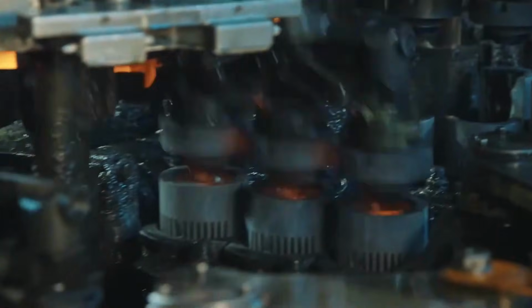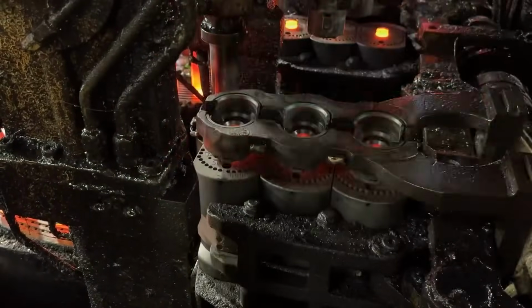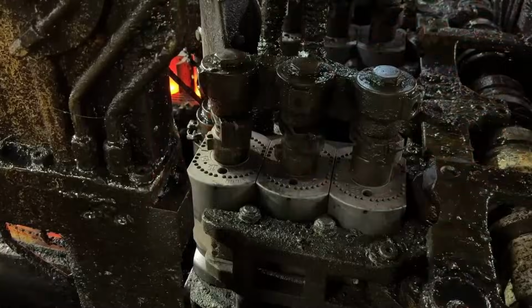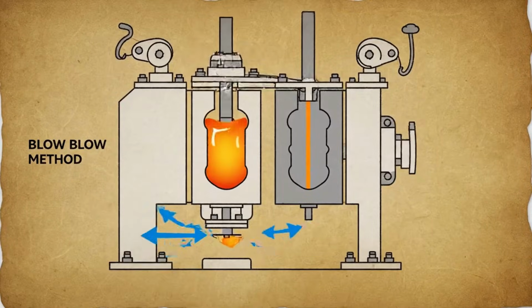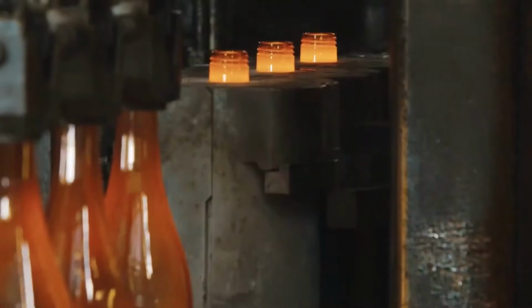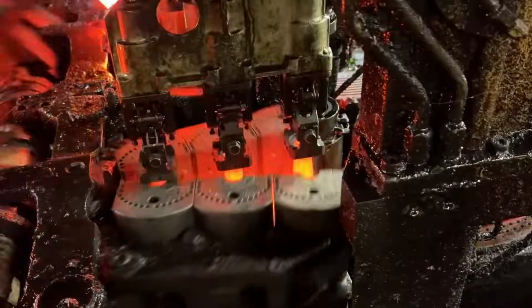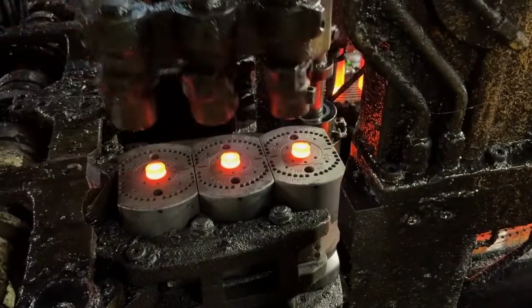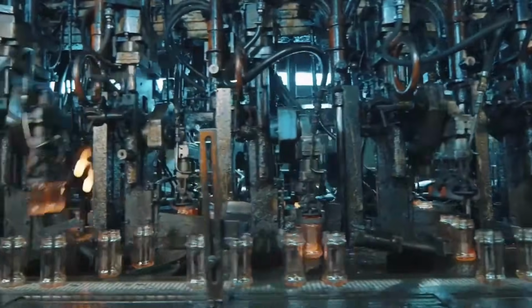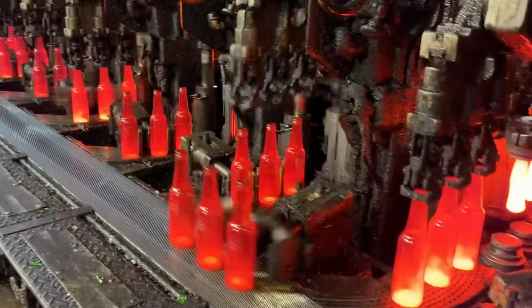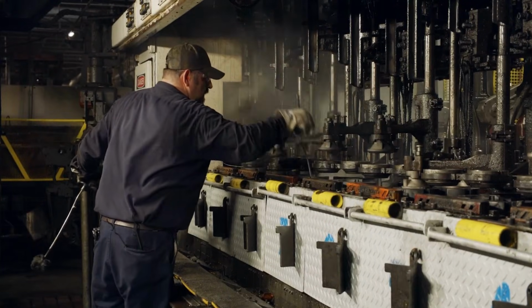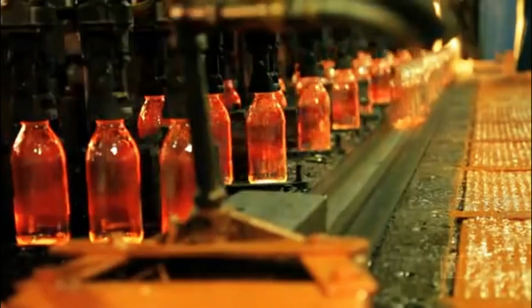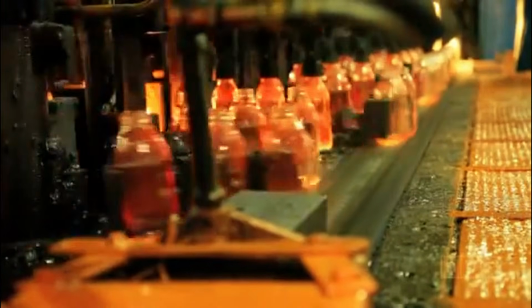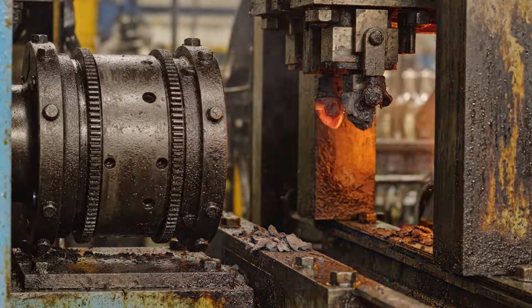A burst of compressed air from above pushes the glass outward, creating a hollow parison, essentially a bubble-shaped preform with a finished neck. The parison transfers to the final mold, where a second air blast expands the glass outward until it conforms precisely to the mold's contours. Every valve and sensor in modern bottle-forming machines operates with timing accuracy measured in thousandths of a second. This precision enables facilities to produce hundreds of thousands of identical bottles daily.